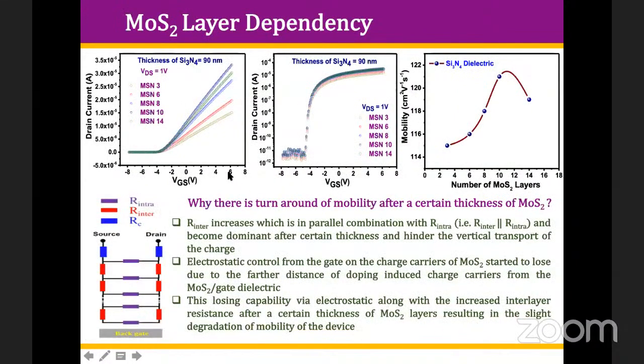Yeah, and then we tried to change the thickness of this MoS2, because we fixed silicon nitride, and the thickness of silicon nitride we fixed at 90 nanometer, and we changed the thickness of MoS2 from 3, 6, 8, 10, and 14 layers. You can see the transfer characteristics here, and the mobility, you can see, we found maximum at a particular thickness of MoS2, around 10 layers of MoS2, and before that and after that the value of mobility is less.